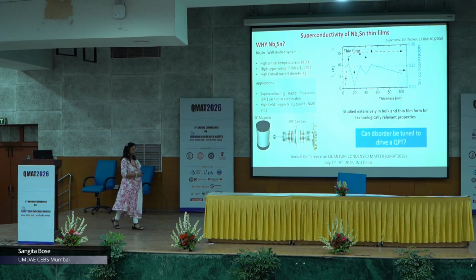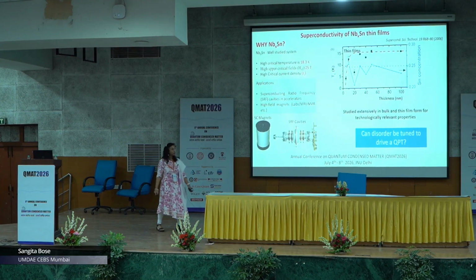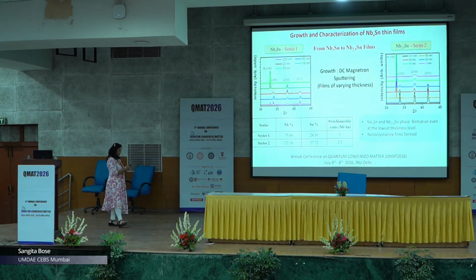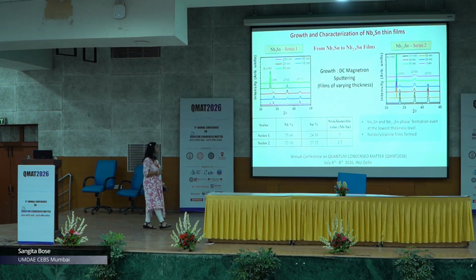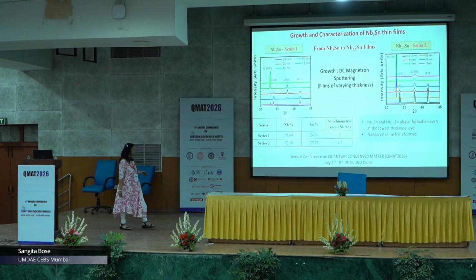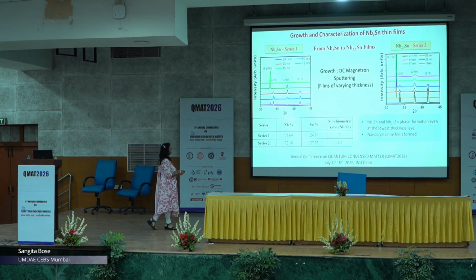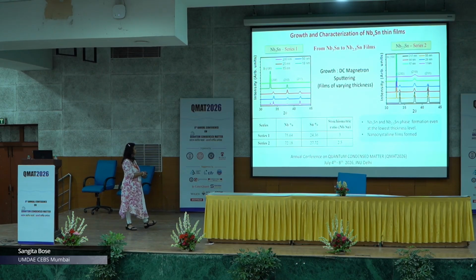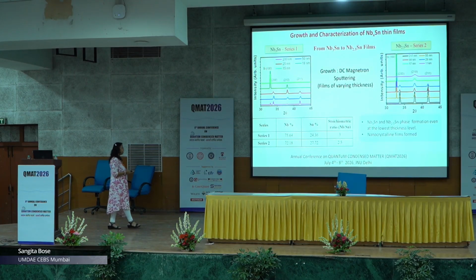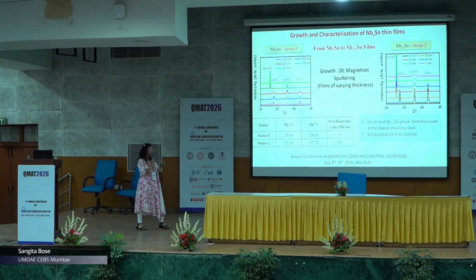Now, our question was, can we tune disorder in these kinds of systems to get a quantum phase transition? So, with this we made two kinds of niobium tin thin films, one which is of course the stoichiometric ones, and the one which is slightly off stoichiometric, which is a bit tin rich. So, we had 72 to 28% of tin. And of course, we see that more or less you get similar phase, similar XRD patterns in both of them. Now, an important thing to note is that there is a bit of peak broadening in the XRD which we observe as we decrease the thickness of the films, and that tells you that these films which are forming are basically granular in nature, where the grains are extremely small in size.